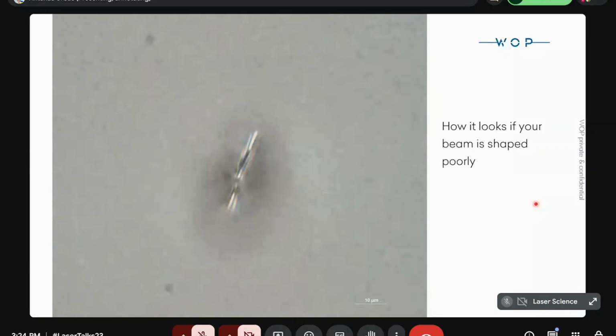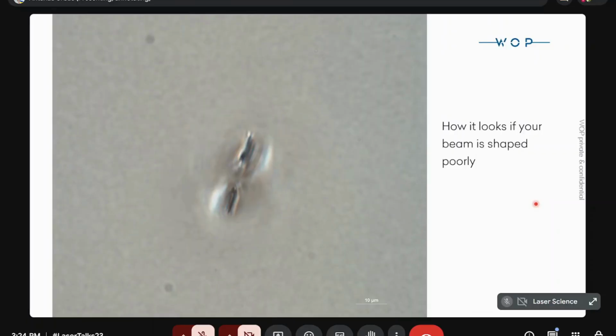And if your beam is shaped poorly, you can see how it looks inside of the glass. This video shows you modifications and cracks every 50 microns going down from the top surface. You can see that there are sometimes very well-defined directions of the cracks, but these are not the same at different depths.